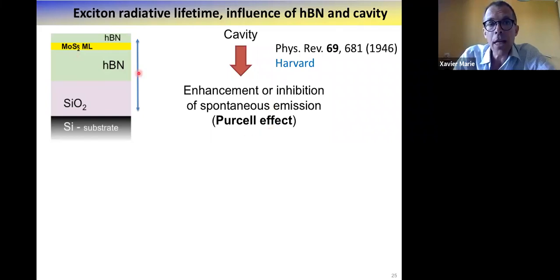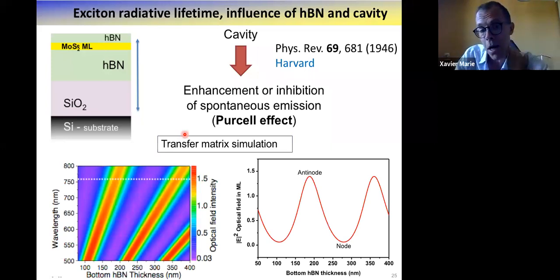And indeed, in our case, what is the emitter, what is the mirror in the classical structure I have shown you? Basically, the emitter is a monolayer, which is almost at the top of the structure. The top HBN is very thin. And the mirror, which is a bad mirror, but it reflects some light, is the interface between silicon oxide and silicon. So what we can do is control the distance between the emitter here and the mirror, the bad mirror, but it's a mirror. And depending on this distance, I will show you that we can control the radiative recombination time. So you can just start with a very basic transfer matrix simulation, showing the Fabry-Pérot effect just at the beginning, as a function of the wavelength and the bottom HBN thickness.